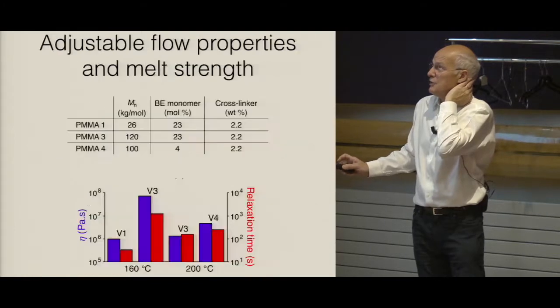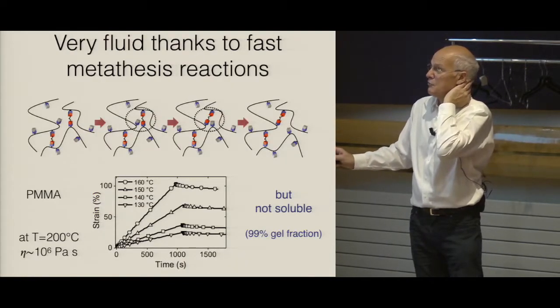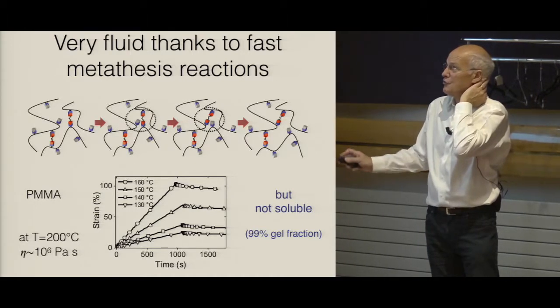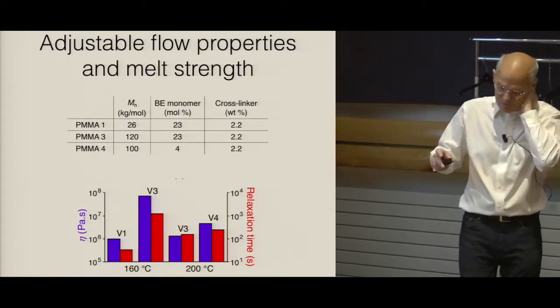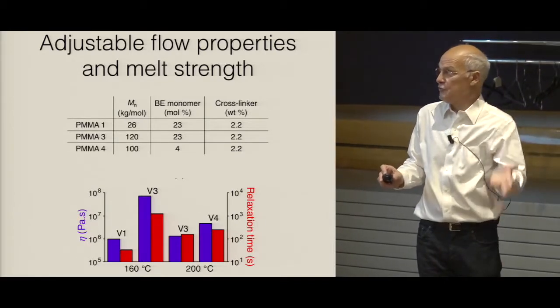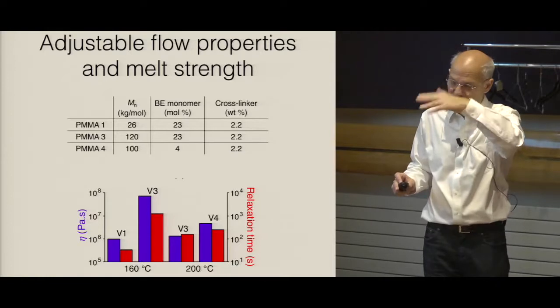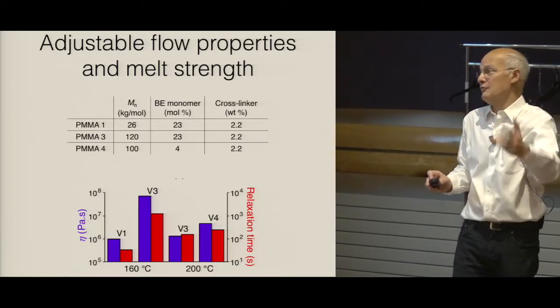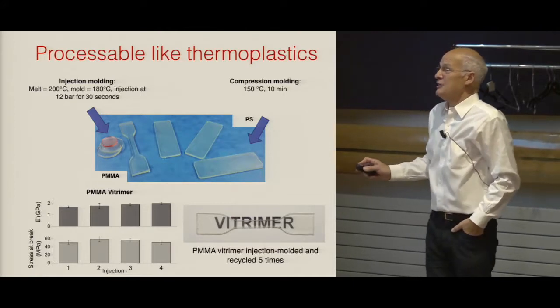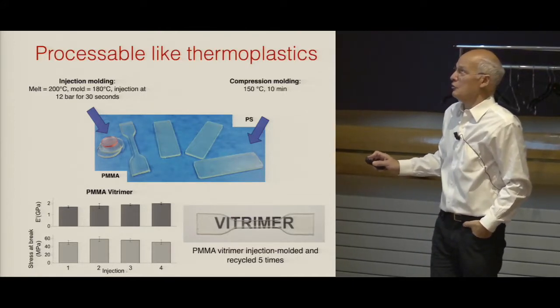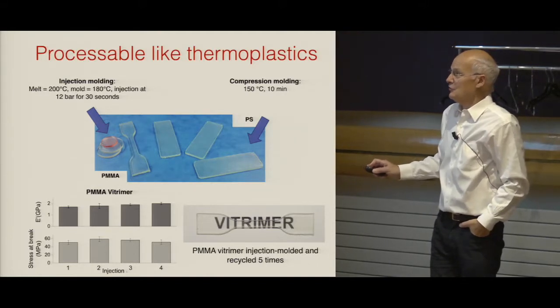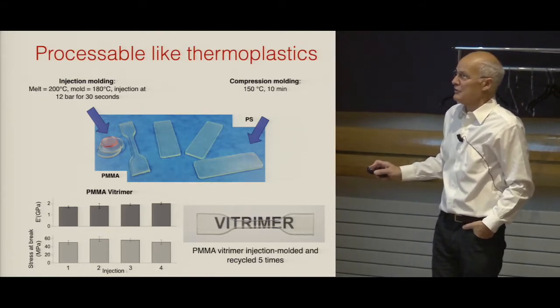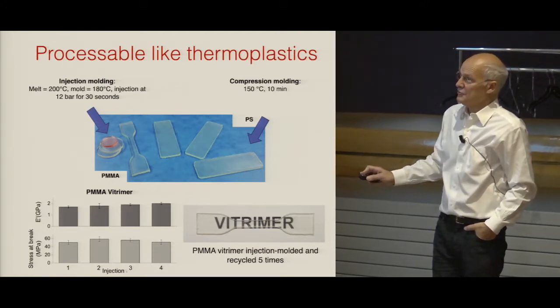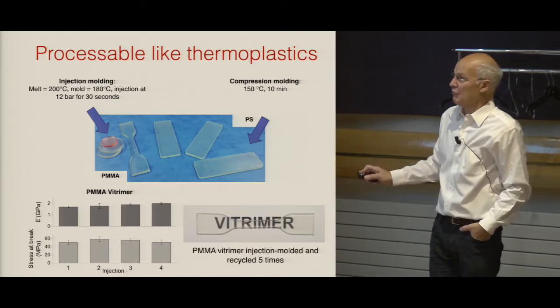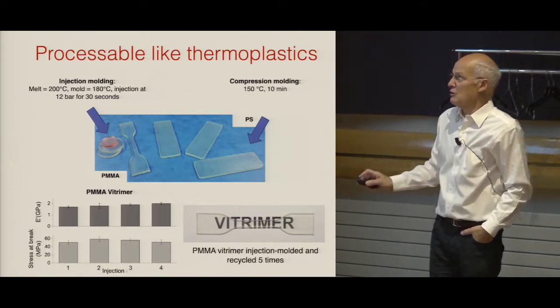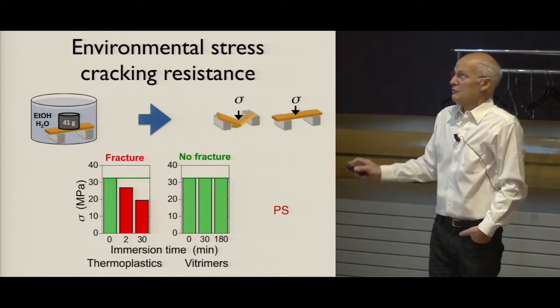And there are many parameters that can be adjusted in the system, because you can adjust the number of grafted groups, you can adjust the number of crosslinks, and so you can choose the properties you want: how fast you can process, and the compromise with the degree of crosslinking you have. And the idea is that you can injection mold the system, or you can compression mold. And this sample is interesting because it was ground 5 times and reprocessed 5 times. It has the same mechanical properties, but it stays transparent and doesn't become yellow. So these materials are interesting.